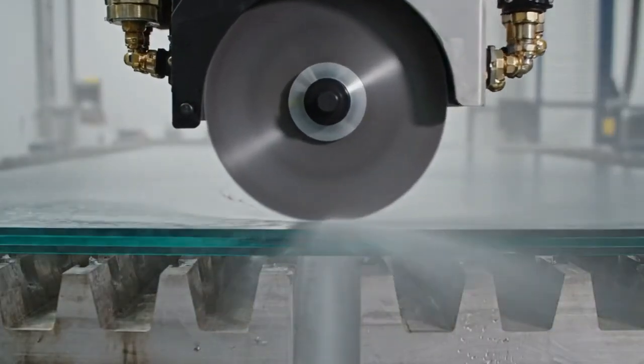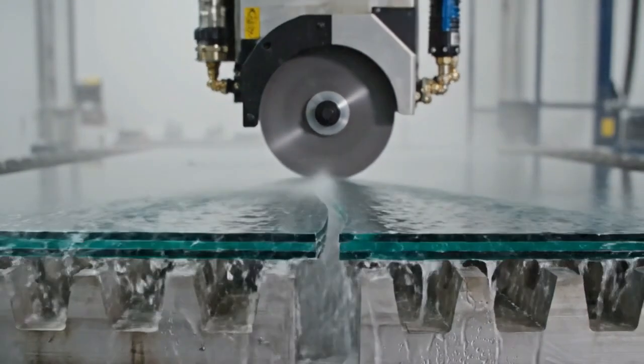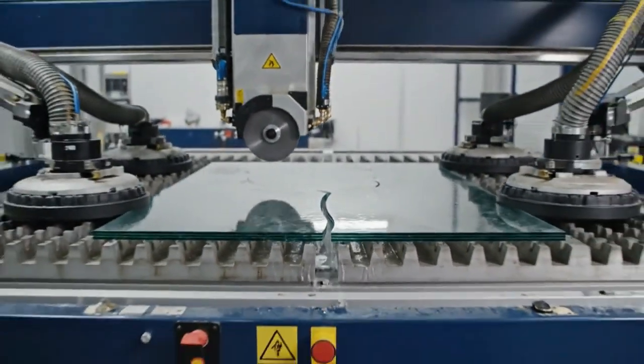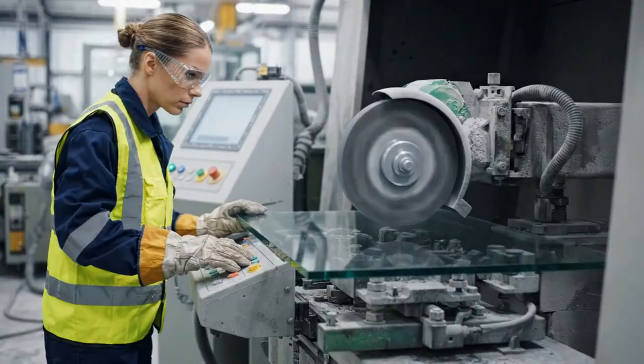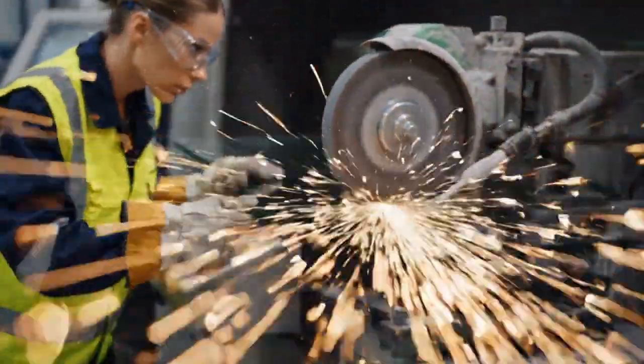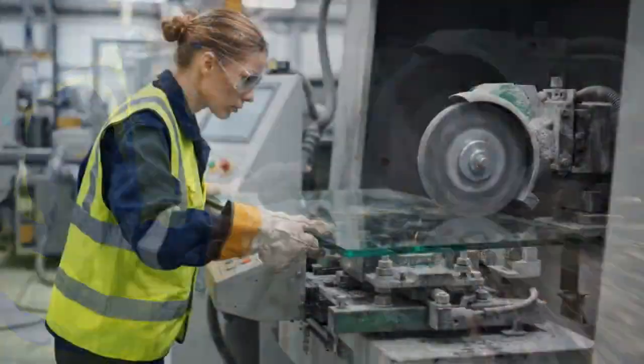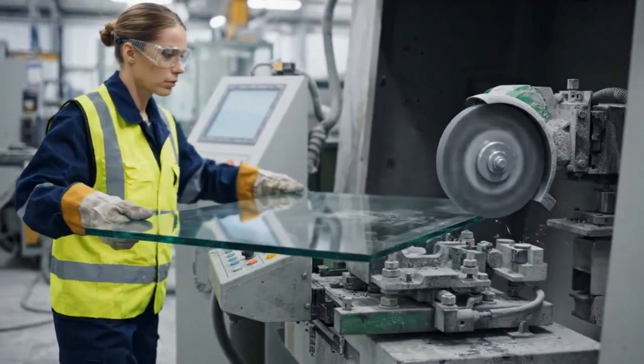The laminated panel is cut to size by the hardest material known to man, diamond. Every edge is ground to a precise bevel, and a micro crack at the edge could grow during flight, shattering the window. Imperfect edges are death.